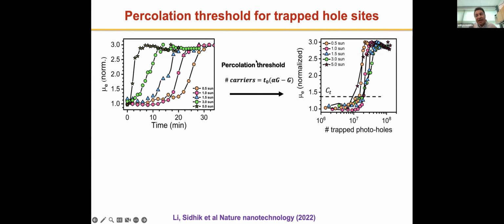And so based on this idea that you are trapping your holes on the iodide upon photoexcitation, you can come up with a very simple type of model, which is based on just hole trapping, just like you would use in a semiconductor where you have the holes being trapped by a defect state. And you can end up with a curve which looks something like what is shown here. And you can see that for all these excitations, there is a certain amount of trapped photohole density that you need, which is about 10 to the 7 photoholes.